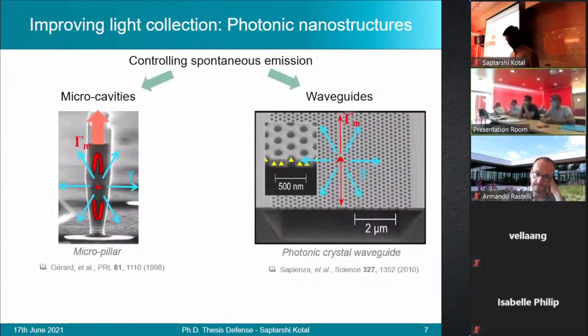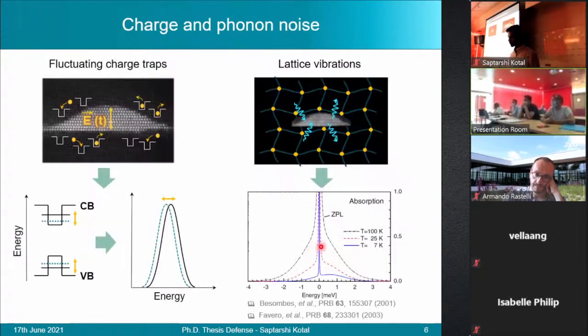The second effect that we observe is the actual broadening of the zero phonon line itself. This happens due to quadratic interactions between the emitter and the surrounding. It is associated with phonon scattering of the exciton, which is excited by virtual excitation to higher excited states. Such a process generally involves much higher energy phonons, and therefore we don't generally see this effect at cryogenic temperature.